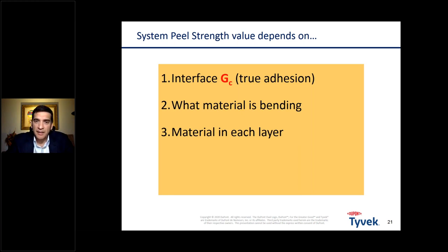And then the material in each layer is important. Let's say we have a five-layer material, and all five layers have the exact same thicknesses, but one has a nylon core and the other, let's say, has a polypropylene core. Not a very common structure, but just for an example. The mere fact that there's a difference between the two in terms of stiffness and their interactions with the other layers means we will get a different seal strength just by changing the material in the layer. So it's not just the surface that will give you a difference. It's also the rest of the film that makes a difference in what your seal strength value will be.